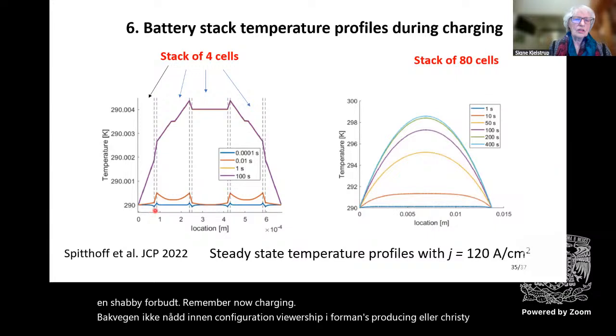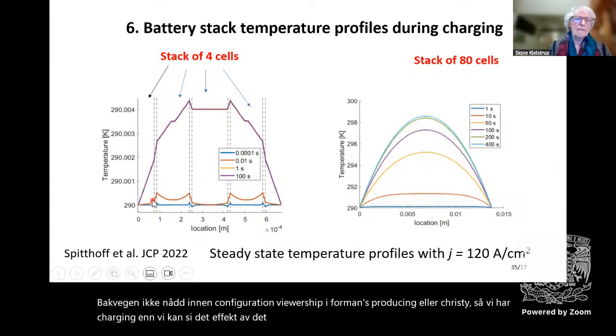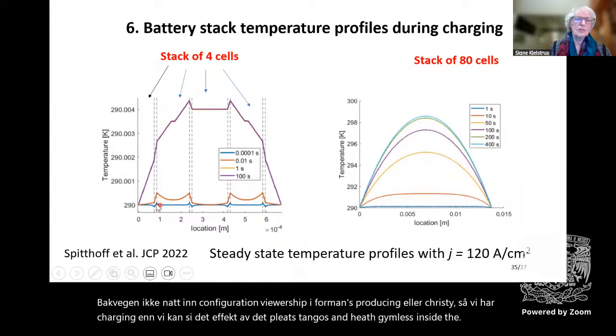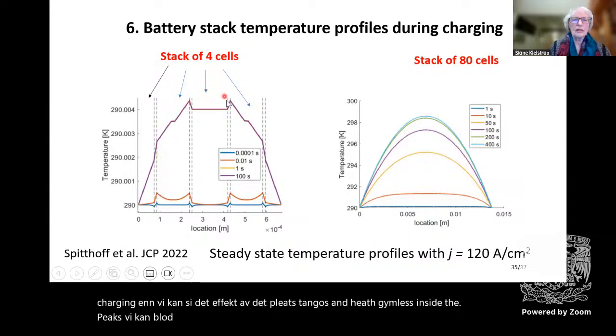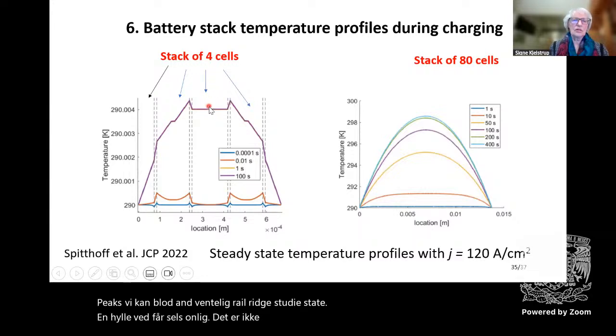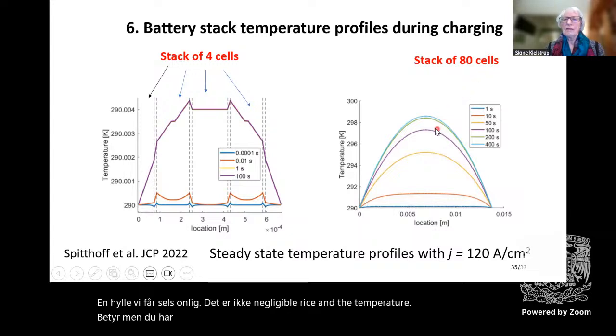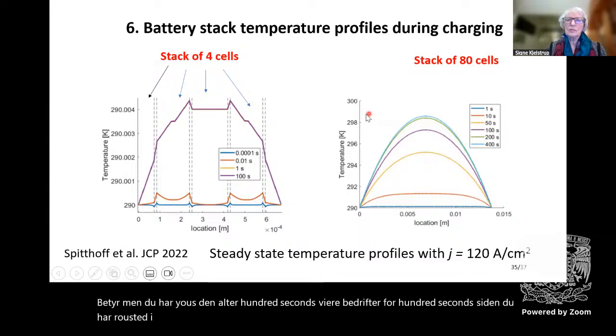So we are charging, and we can see the effect of the Peltier heats. But as time goes and heat accumulates inside, the peaks become blurred, and eventually they will reach a steady state. And here, with 4 cells only, there is a negligible rise in the temperature. But here, when you have 80 cells, after 100 seconds we are here, but after 400 seconds we seem to have arrived at a steady state. And this temperature is more than 8 degrees above the temperature on the 2 sides that we started with.